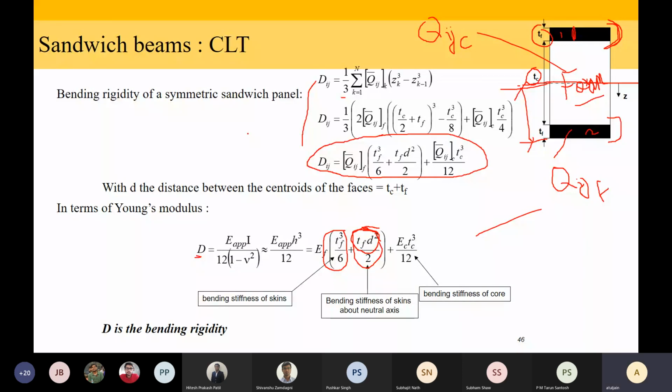The plies are well bonded, that is one. The laminas are well bonded, this is one. Then the plies must be very thin. And one more, it must not have a large stiffness difference. So consecutive layers must not have a very high stiffness gradient.